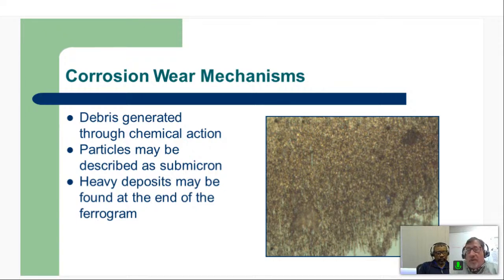Here's the other end of the scale, right? The corrosion wear mechanisms where you might be hard pressed to actually come up with a measurement. It might be so small you almost can't even make the particle out. That is correct. And typically that's at the exit end of the ferrograph, not at the entry where it first starts. Because they're so small, they stay in suspension longer and finally get pulled out of the slide. But these might be submicron. They may just look like a blanket of material, but it really is these tiny, tiny particles. And knowing that that's the wear mechanism is really important in knowing what to do next, right? Yeah, that's correct.